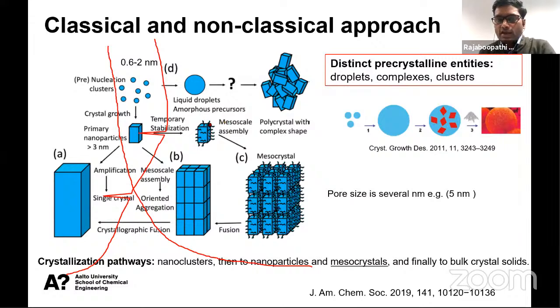So here, to stabilize the nanoparticles, you can use different additives, different surfactants, or different polymers to get mesocrystals. Based on the stability, it will produce mesocrystals. For example, if you don't stabilize the nanoparticle, it will produce oriented aggregation. Suppose once the mesocrystal is formed, but still it is not stable, it will fuse to oriented aggregation. If the oriented aggregation is not so stable, again it fuses to a single crystal. So there are some possibilities. The thing is, we need to stabilize the nanoparticle to get either oriented aggregation or mesocrystal.